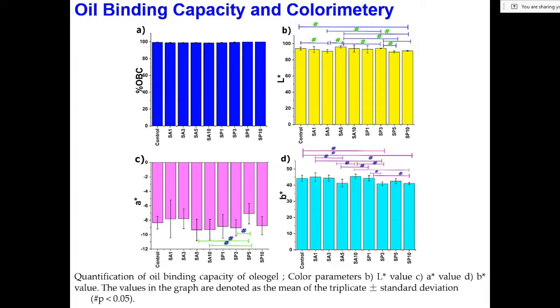We analyzed the colorimetry and the oil binding capacity of the gels. Now, why do we want to perform the oil binding capacity? This is because the higher the oil binding capacity, the longer will be the stability of the oleogels. Why? Because if the oil binding capacity is lower, the oil would start syneresis from the gel systems and come out on top, and you will see a layer of oil depositing over the gel-based system. So that is a sign of instability.